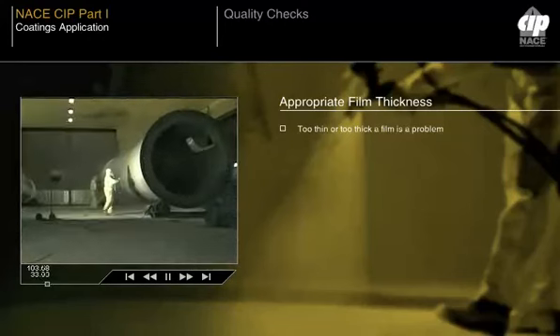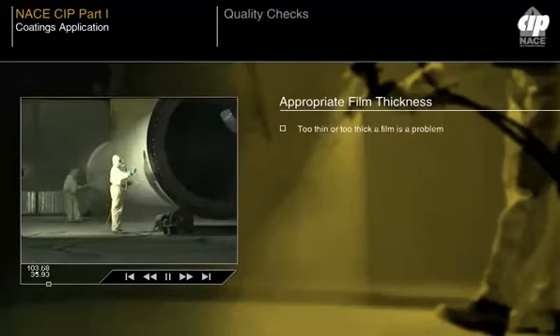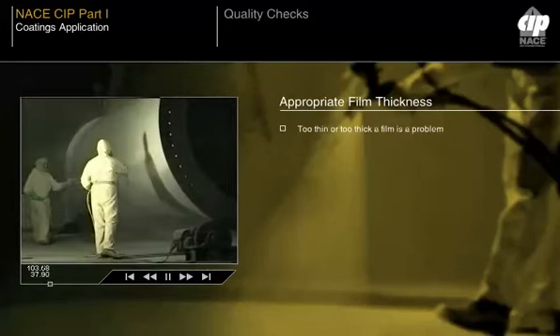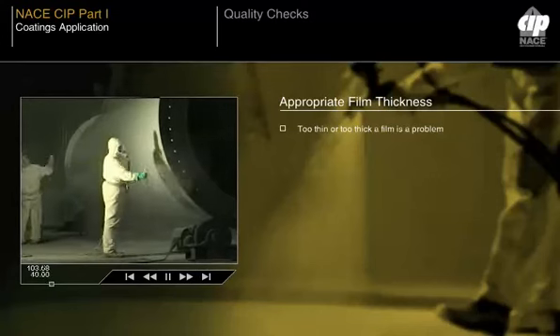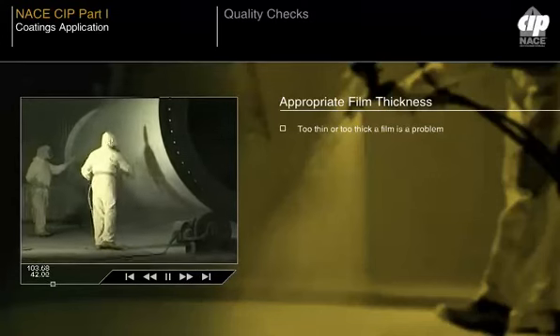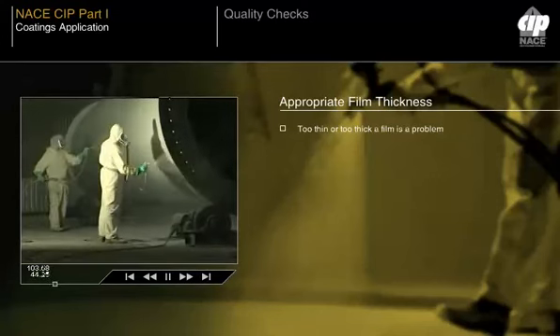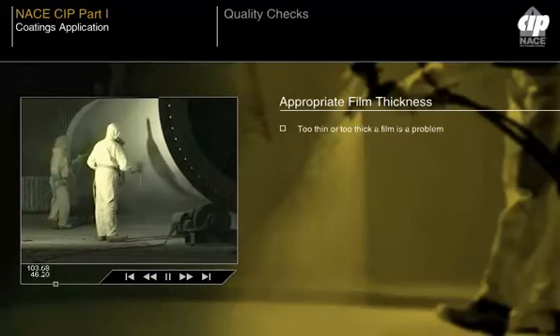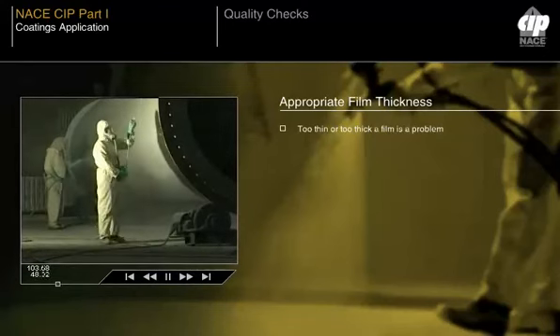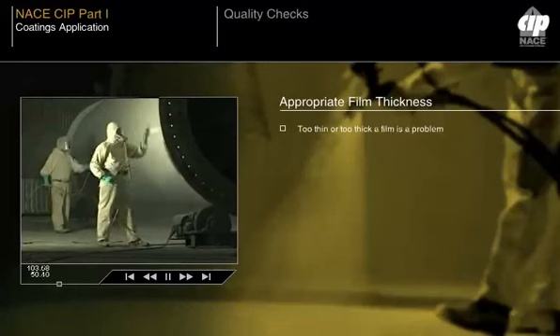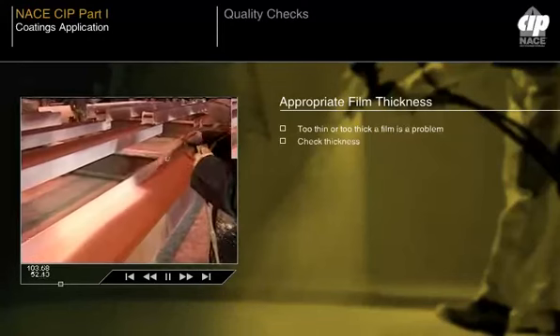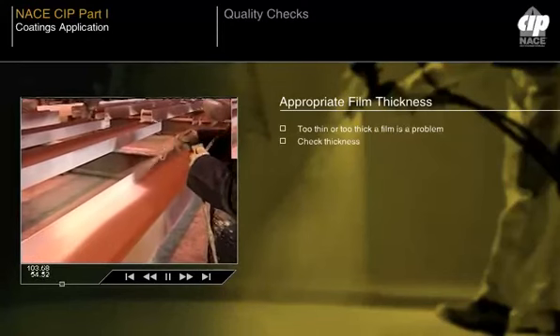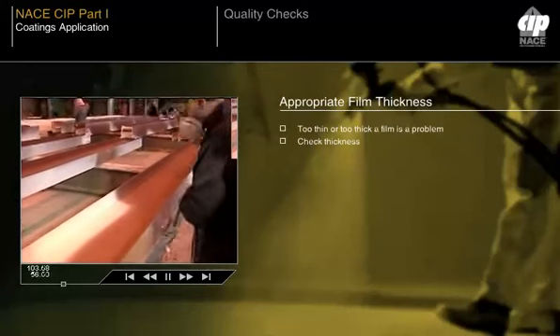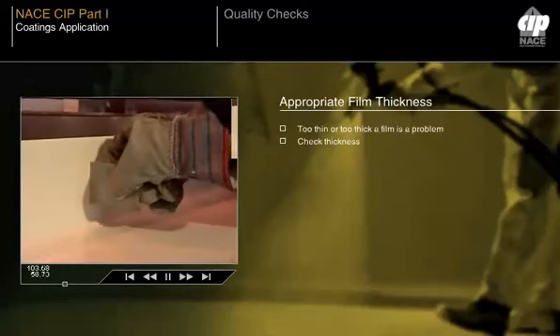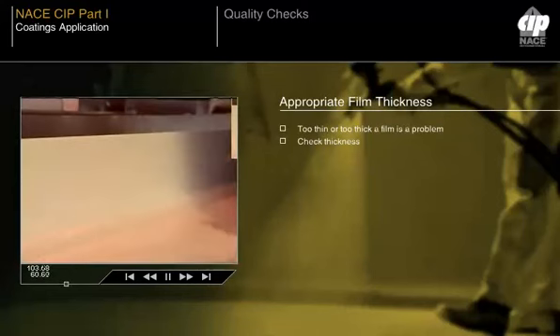With polymerized coatings, particularly those intended to be applied at high DFT, 20 mils, 500 microns per coat or more, there may be internal shrinkage due to the excessive thickness, leading to cracking, flaking or delamination, loss of adhesion. Care should be used to ensure that the application stays within the recommended parameters, particularly film thickness.